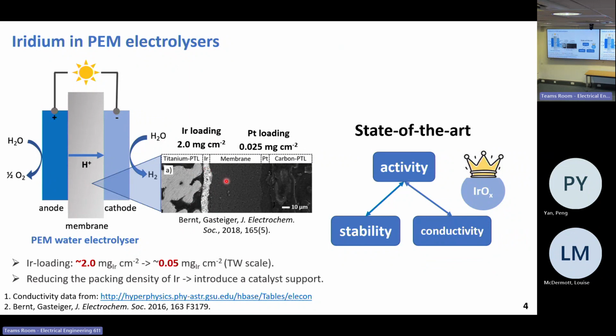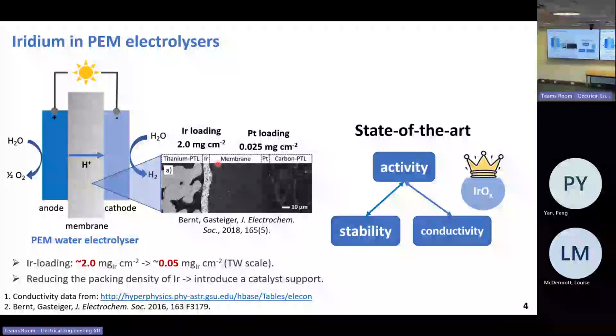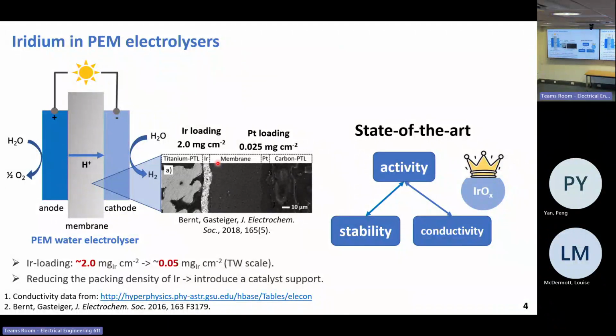Recent analysis showed that if we want to meet global energy demand on a terawatt scale, considering the annual production of iridium, we need to reduce iridium loading by a factor of 40 to 50, from 2 milligrams per centimeter squared to 0.05.